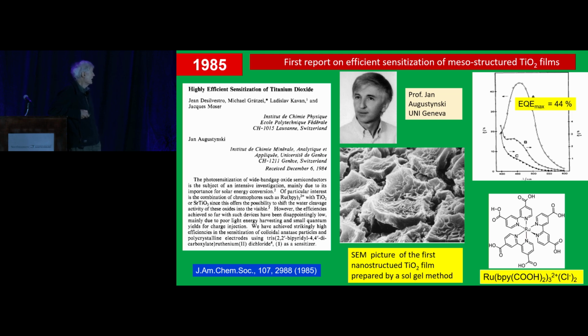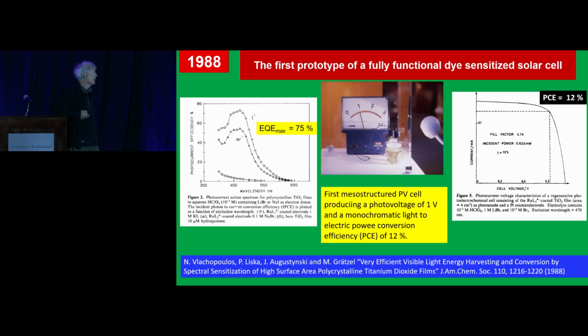We could get external quantum efficiencies of 40%. That means a fraction of 40% of the incoming photons of a certain wavelength, a maximum in this spectrum, were converted to electric current. That encouraged us to build a device, and that gave even better results, 75% of the incoming photons. That was at 450 nanometers. That was not across the spectrum.